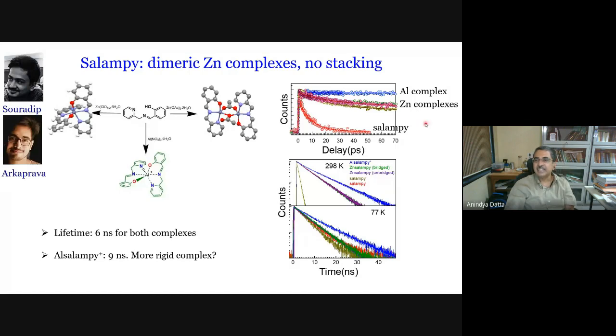And the result is that we get significantly stronger, longer lived excited states for the zinc complexes. It perhaps shows up better in nanosecond time scale. This is the fluorescence decay of the zinc complex. Both the zinc complexes have the same lifetime. This here is the fluorescence decay of the aluminum complex. The lifetime is 9 nanosecond. With Schiff base, the lifetime of zinc complex was like tens of picosecond, and now we have 6 nanosecond. So the difference between 6 and 9 is significantly less than the difference between tens of picosecond and 1 nanosecond that we had between zinc complex and aluminum complex of the earlier Schiff base. So it looks like if we avoid pi stacking, we do get longer lifetimes.